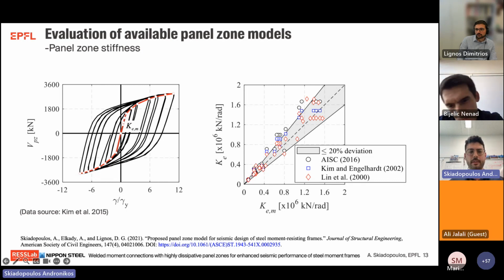In the vertical axis of the right figure, we compare the predictions of available panel zone model equations. What you see here is that available models like the American code or the Kim and Engelhardt model tend to overpredict the panel zone elastic stiffness by more than 20%, and this is because these models assume shear deformation dominance within the panel zone. However, models that explicitly account for the bending deformation mode within the panel zone provide a better performance in predicting the panel zone elastic stiffness.